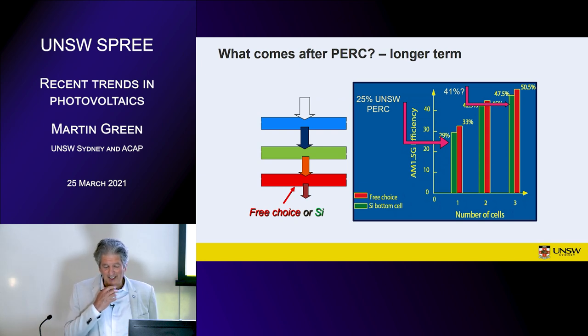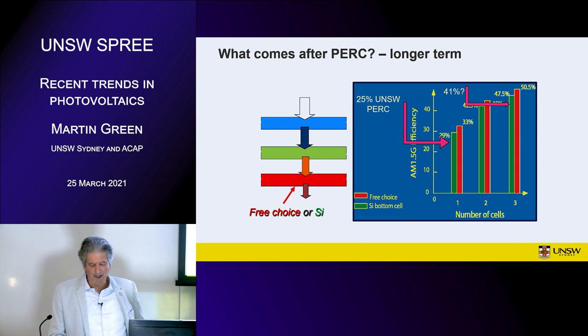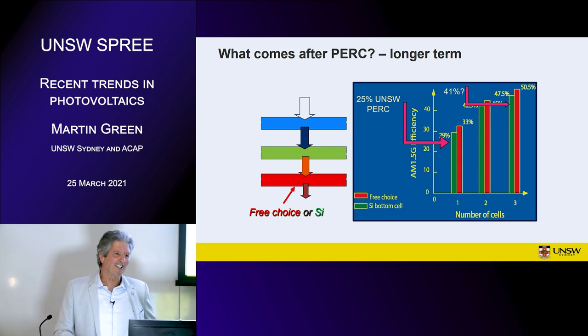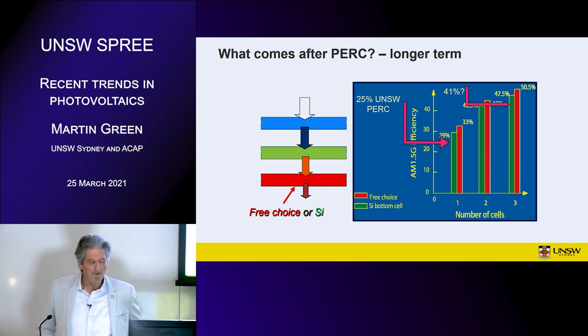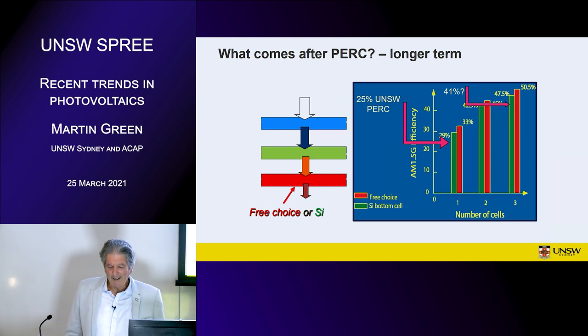And this is how much you can get. And it also shows that silicon's a good choice for the bottom cell, at least if you're only stacking three cells together. So on the right, just showing the limits. So I think PERC will get to 25% in production, the same as we did in the lab. All the other technologies have done better than the lab performance, so why not with PERC? And if you can get that same fraction of performance with two junctions on silicon, you should be over 40% efficiency at the cell level.